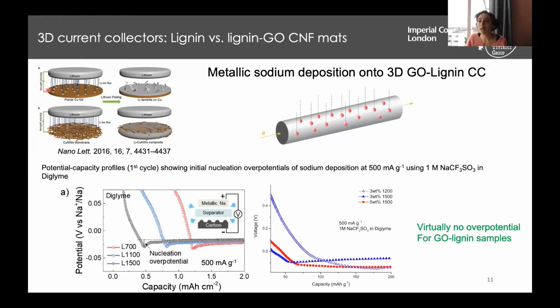So if we have a planar current collector, the metal will deposit on top inhomogeneously. And if this happens over and over again, then dendrites will start growing. Whereas if we have a three-dimensional porous host, this ion flux will be much more homogeneous, and then the plating of the metal will occur more evenly and without the growth of dendrites.